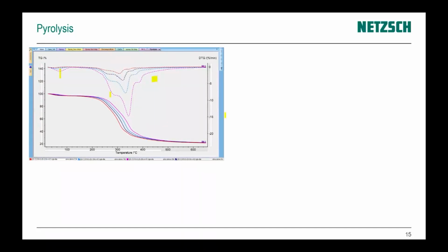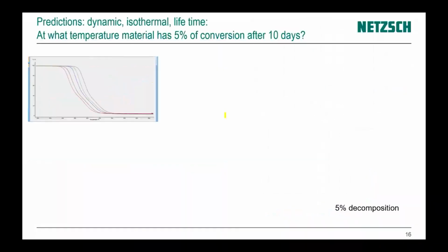That was pyrolysis, one-click result. Now we can make predictions of our data. It could be dynamic predictions, isothermal predictions, lifetime predictions. Dynamic predictions, for example, for a given heating rate. What will be decomposition at that heating rate? Let's see, 0.5 K per minute, which was not measured here.